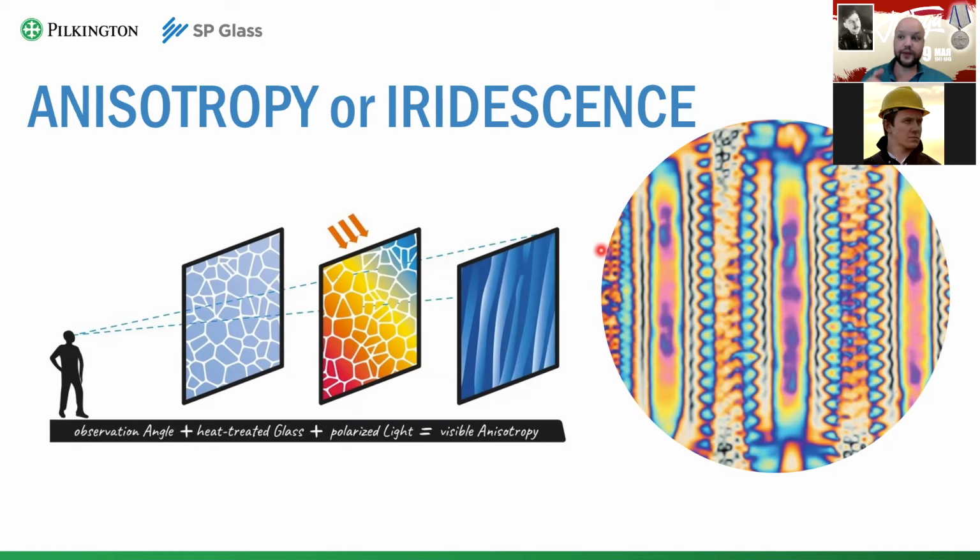The most important word in this case is rapidly. When we cool it down, air comes through the holes in the cooling tubes, and the glass is just moving under it. Some parts of the glass are chilled faster than the others because of the air distribution. And that creates an anisotropic distribution of stress on the glass.